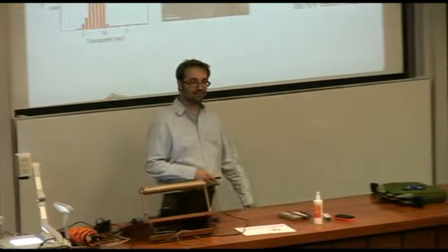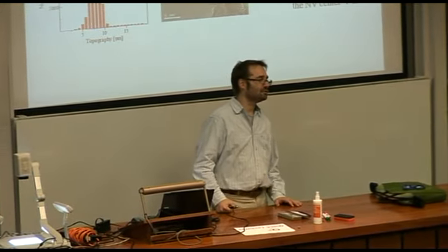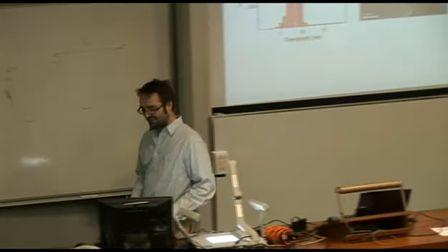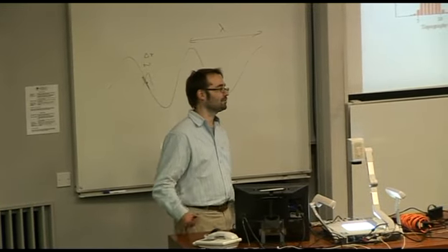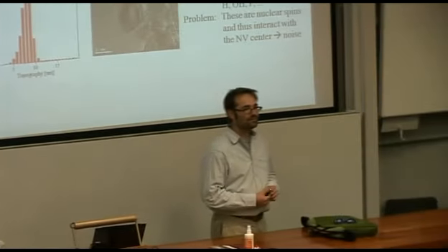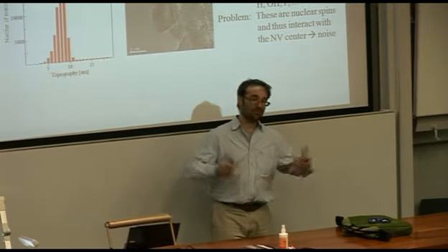You use all sorts of acids, and once you have burned away the graphite, then you have to somehow treat the surface to make it regular. What people do, for example, is they take, I keep forgetting the name in English, HF. That's an awful acid that you use. So you can use that, and in the end you can cover the surface of the diamond with fluorine atoms. Then it's a bit like Teflon, more or less. So it doesn't stick to very much anymore, and it's a very well-defined surface because it's all the same fluorine atoms. The problem there is that the fluorine atoms have a nuclear spin themselves, and therefore they will flip-flop around and they will create noise.